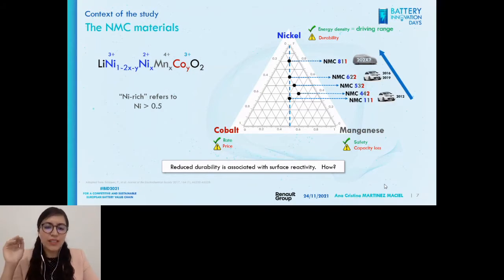So it has been, for the last years, this trend of increasing nickel content. However, this has a disadvantage, which is the durability of the batteries. It has been observed that when a higher nickel content is used, for example 811, the durability is reduced. And very often in the literature, it is said that this is because of the surface reactivity. So the question for my thesis was: how is the surface reactivity affecting the durability of these batteries?